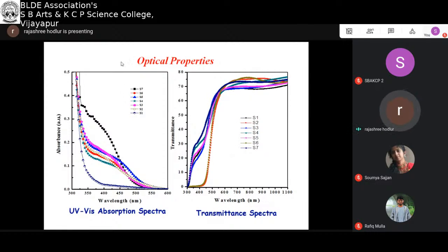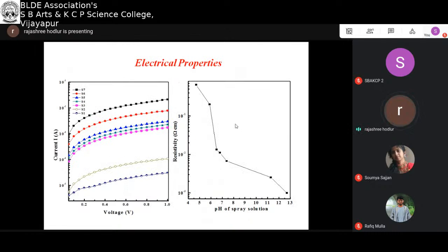So since cadmium oxide belongs to the TCO group, that is the transparent conducting oxide group, we studied its optoelectronic properties. So we can see here, just by varying the pH, even its absorption edge was slightly tuned. And this transmittance spectra graph clearly shows that it acts as a transparent material in the visible region, that is above 500 nanometers, with tuning as we varied the pH of the spray solution.